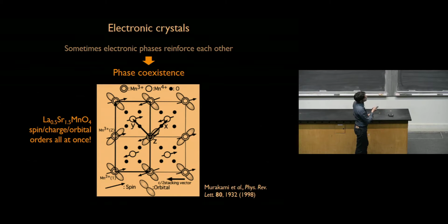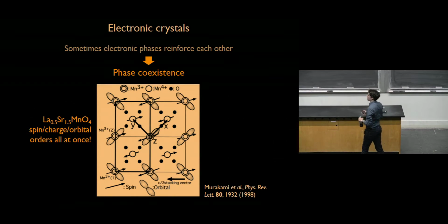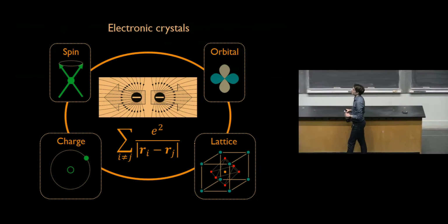And then you have antiferromagnetic order. You see the spins here. And you also have charge order, because you have an alternation of an oxidation state of 3+ and 4+. So you have different charge states for the manganese. They all form ordered phases. So you see, you can get this very exotic type of electronic ground states.